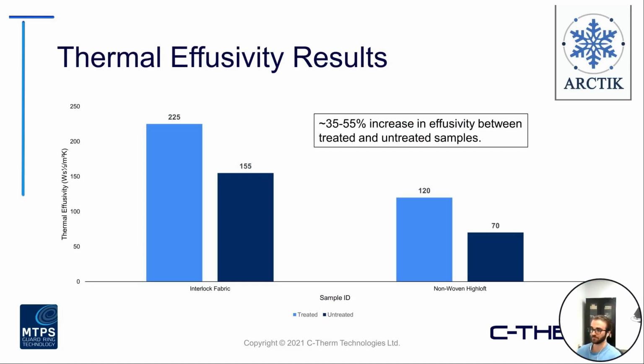Just taking a look at a couple different samples, so an interlock fabric and a non-woven, both treated and untreated. And across both cases, there was a notable difference in thermal effusivity from the control to the treated sample. In this specific case, ranging about 35 to 55% increase between the two.